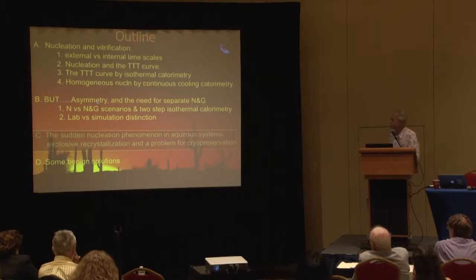And there is here a distinction, not so much between what Valeria showed us, but between most of the previous simulations, which, when they're exploring the behavior of a crystallizable sample in a computer box, the box only has 1,000 particles or something, very, very many smaller than hers. And so most of the previous work has examined just the formation of a nucleus, not the nucleation and growth. So I don't know of any computer experiment, although I think Valeria could do it, in which this distinction between the nucleation and the nucleation and growth, and you implied it actually in a way, quite directly, but you didn't show what the sort of combination of TTT curves which I've just been dealing with.